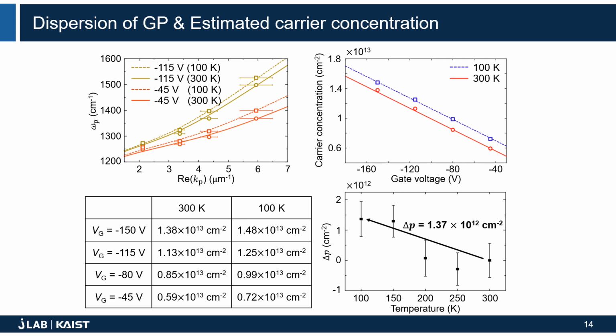The amount of the additional hole doping is about 1.37 times 10 to the 12 per centimeter squared. We speculate that the additional hole doping could originate from the release of trapped charges at the graphene silicon dioxide interface, because this cooling-induced doping didn't appear when the graphene sheet was encapsulated by hexagonal boron nitride.